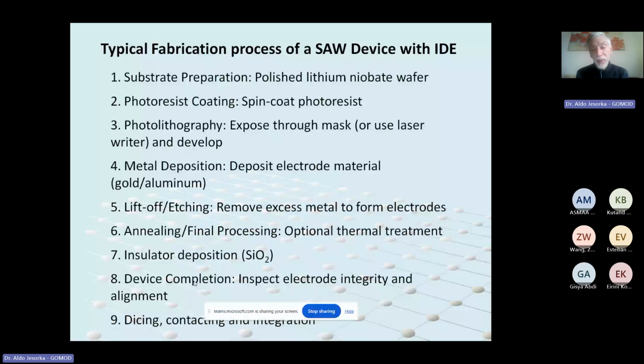That is typically several micrometers of silicon oxide. Micrometers is ideal, also because of the temperature compensation, but it's typically very much disliked in the clean room to deposit that large amount of silicon oxide. So with 100 to 200 nanometers, you can already get pretty good performance. Then device completion: you inspect the electrode integrity, you see if they have a resonance in air, and then you can dice, contact, and integrate in whatever device you want to use.